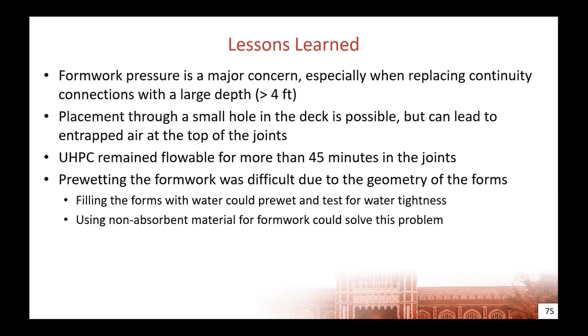And then lastly, there is the issue of the material being pulled off of the formwork. That tends to happen, especially whenever you use something like plywood that will leach moisture out of the material. So the best way to mitigate this is to either coat it with a polyurethane or just pre-treat it with water, so that it won't suck the moisture out of the UHPC that's placed against it.